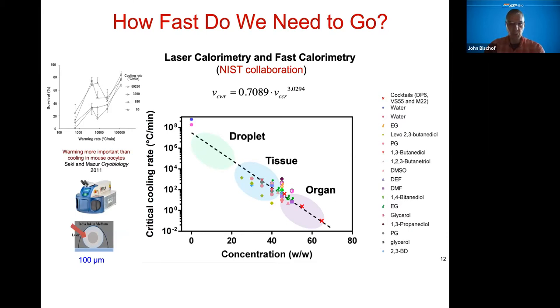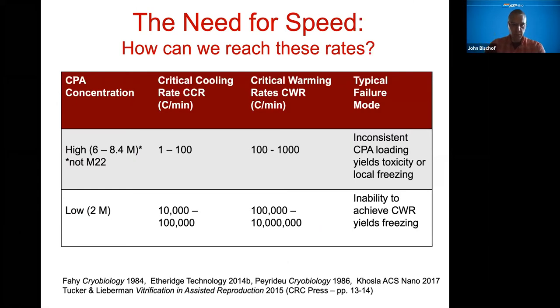And so the rate is really, really important. This is just a slide to put it a little bit into context. If we're in this really high concentration regime, something like you might need for an organ, the critical cooling rates are going to be roughly 1 to 10 C per minute. And then you're going to need to come back at 100 C per minute, maybe even a little bit higher. For low concentration, and this might be a cell type that's very precious or rare or sensitive, you're not going to be able to load it with 8 molar. So you're going to go to a lower concentration, but the price you pay is that you need to go at faster rates. So 10,000 to 100,000 C per minute on the way down, and maybe all the way up to tens of millions on the way back up. So this is just something to keep in mind.